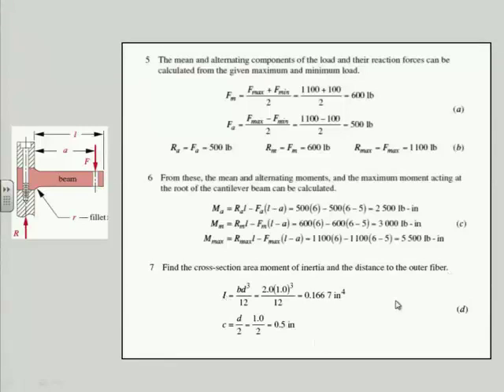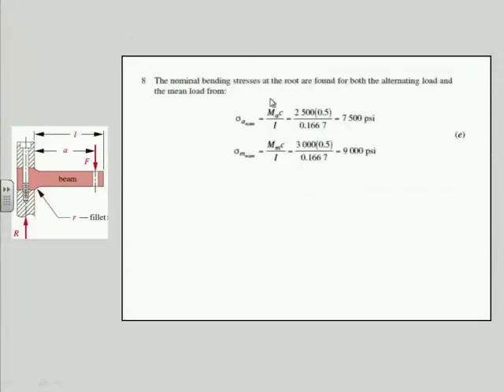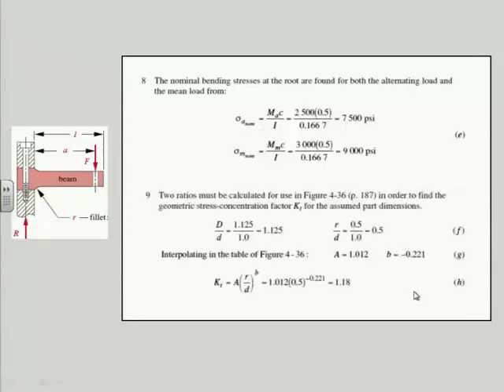We calculate the cross-sectional properties. This is a beam in bending, so I need the I, not the J. The J is for torsion. And that's, in this case, BH cubed over 12, since it's a rectangle, so I get that number. C is the distance from the neutral axis to the outside surface, which is just half of the thickness in this case. So that's a half an inch with my assumed 1 inch. And now I find the nominal bending stresses at the root of the cantilever in the notch. MC over I in both cases. The only difference is this is A subscripts and this is M subscripts. And the numbers are different. So I get 7,500 and 9,000 psi respectively for those two values.